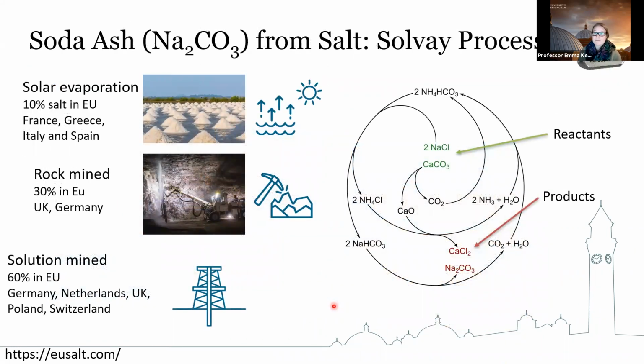So if we look at how sodium carbonate is made, which is the main material that we use for manufacturing of other types of materials, then I mentioned the solar evaporation, which is used quite heavily in Southern Europe, for example, where highly concentrated salt can be the water evaporated off and you're left with these little piles of sodium chloride. We also have rock salt, and Cheshire in the UK for many years was a big rock salt mining area, with caverns up there in the northwest. They're actually now used for storage of documents, because it keeps away the moisture very well by having large salt mines. And you can also do the similar solution mining. And what I've done here is just given you an idea of the different types of mining that are done in Europe for sodium chloride.